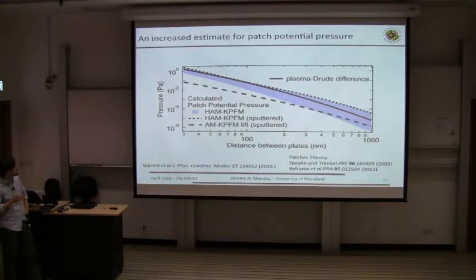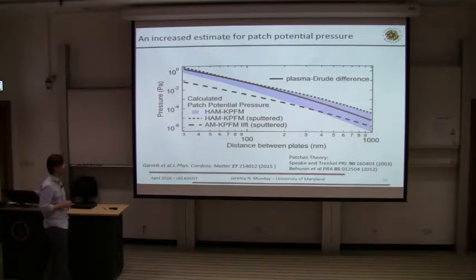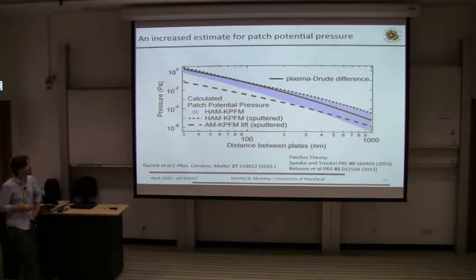So this is looking at a pressure based on this patch potential as a function of the distance separation here. And so here are some of the theory papers that we use to do these calculations. And so you can see that for the measured range, so this shaded region here, these are from a bunch of different samples using different methods. So we got a range of patch potentials here.